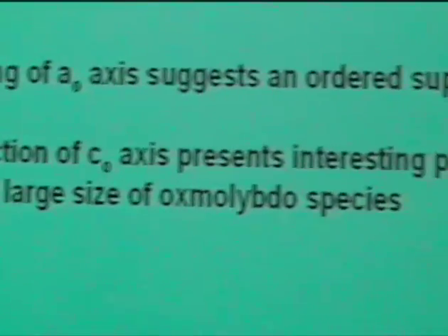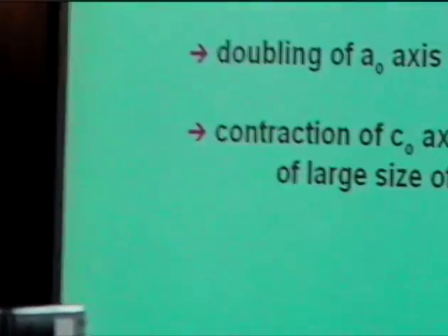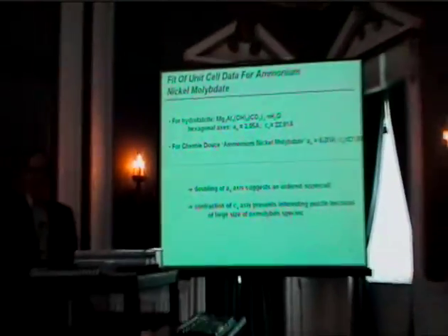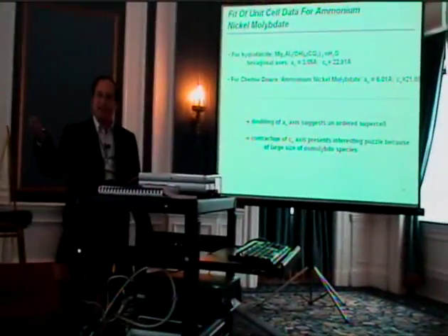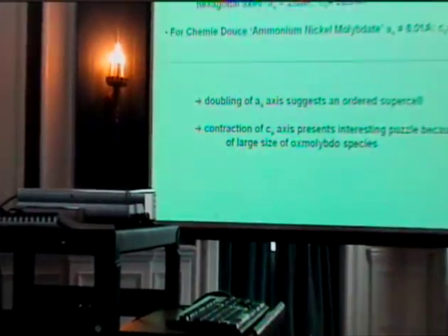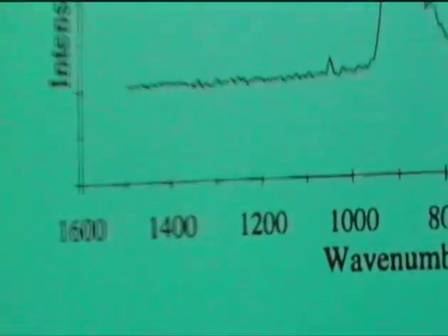The Chemie Douce, kind of interesting, the pattern looked somewhat the same. The A axis had essentially doubled. The C axis was smaller, so we went, wow. I can understand a doubling, there might be some supercell being formed in here. But how did this thing ever shrink? We went from carbonate to molybdate. Molybdate is a lot larger than carbonate. So that was a very interesting puzzle at the time.